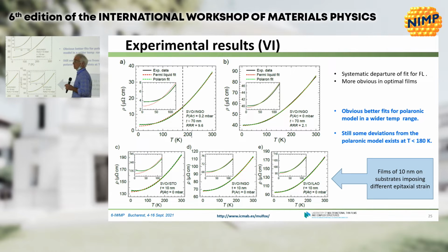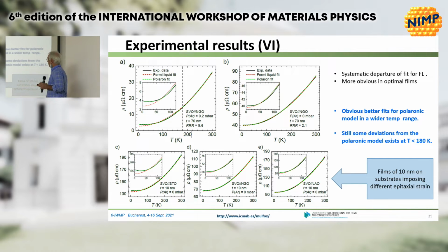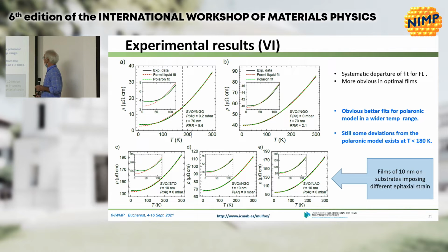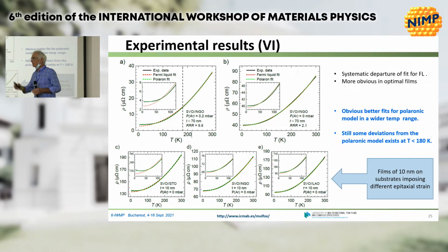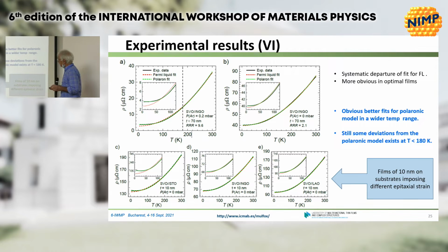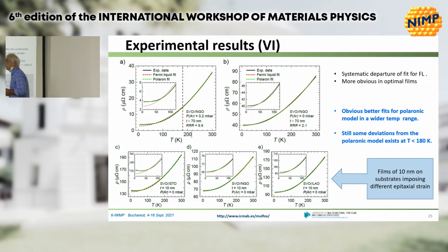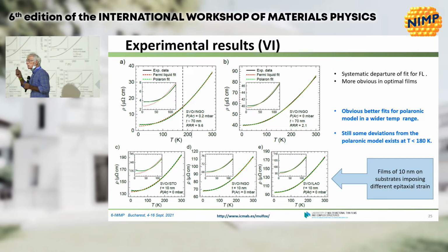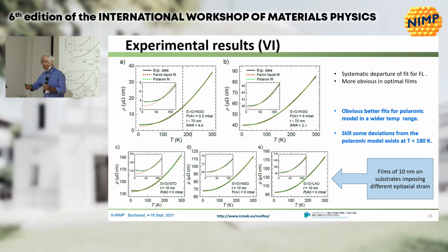So the fit is just perfect. And again, the quality of the fit is better when the films are the highest quality. So it's obvious that the fit works and works better. The fit is just a fit, so I cannot take it as a religion, but the fit is better, no doubt. And it's clear that changing the film on different substrates of 10 nanometers, the fit works. And now I can take this plot or this fit as a fingerprint of the omega 0 on the corresponding film, which is grown on a different substrate.